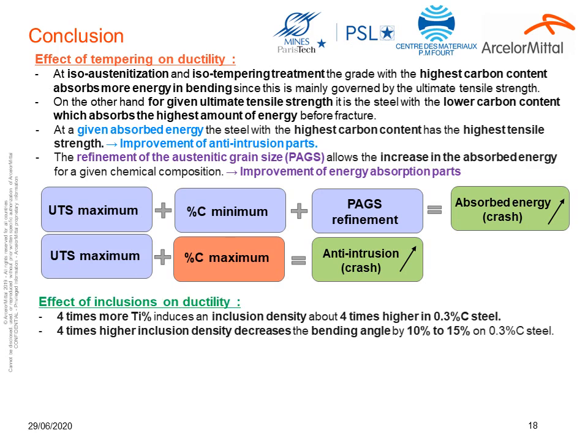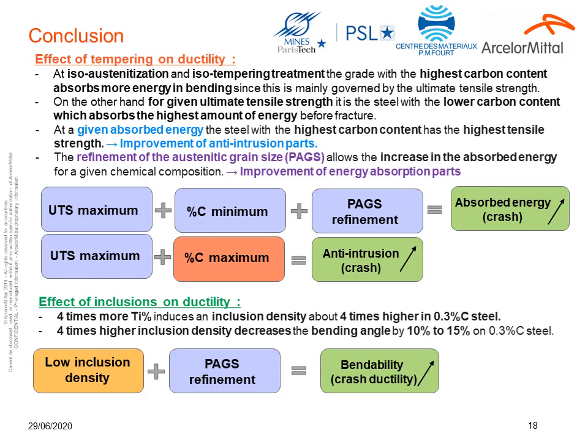Now the effect of inclusion on ductility. We saw that 4 times more titanium percent induces an inclusion density about 4 times higher on our 0.3% carbon steel. 4 times higher inclusion density decreases the bending angle by 10% to 15% on the same steel. Low inclusion density plus grain size refinement induce an enhancement in bendability and consequently in crash ductility.